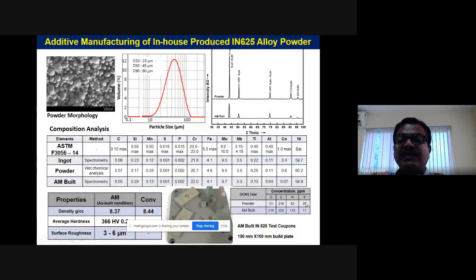Yeah, and similarly, Inconel 625, another superalloy powder. This is also produced in our ARCI in-house, and we could always see that the composition and properties all match with the conventional powders. Even the oxygen content we could get is much lower than the commercial powder. The lower the oxygen content, the higher the purity, and the higher the performance of the materials,